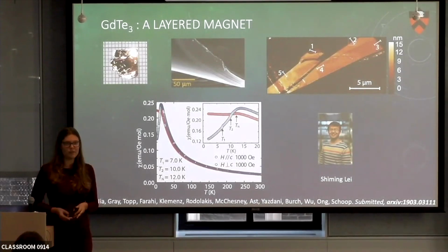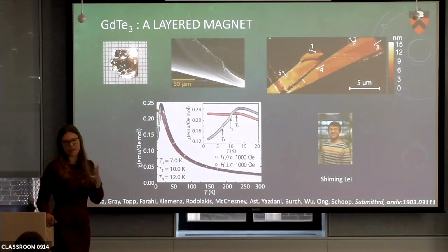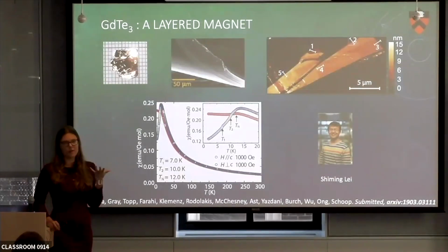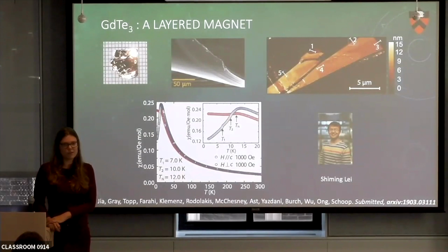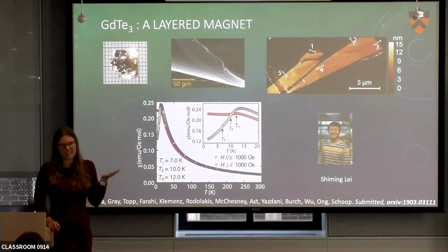a charge density wave. Then if your chemical bonding doesn't fulfill the normal 8 electron count rules, and you have some other kind of bondings, it will always be at the borderline to the instability. But for example, this is not a full-on rule, because then zirconium silicon sulfide should have a charge density wave, but it hasn't, right? Or graphene should possibly have. Every Dirac material, which is a nice material, might.